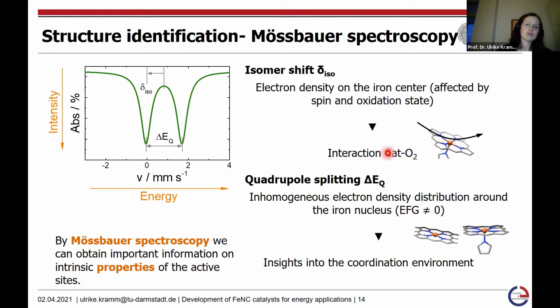And beside that, we have the quadrupole splitting. That is related or basically appears as soon as we have an inhomogeneous electron density distribution around our iron nucleus. Based on that, for instance, square planar coordination of our molecular centers or a five-fold coordination, you would be able to distinguish by the quadrupole splitting. But what is important to be mentioned is always in combination also with the isomer shift. You cannot really analyze these two parameters independently. Nevertheless, when we have these parameters, then basically we can get some nice information on the coordination environment and the electronic properties of our active sites.